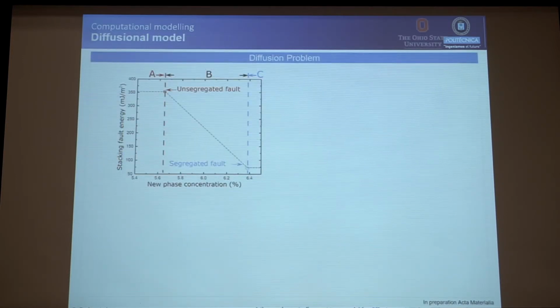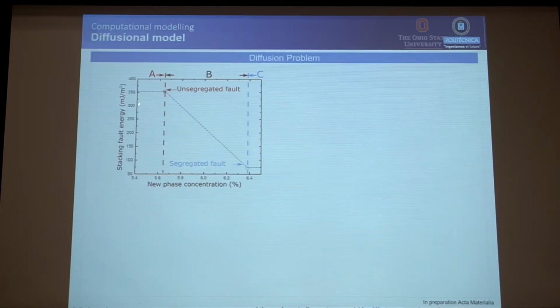So the diffusion field, basically, as I said here, the chemistry, so this is the stacking fault energy, again. So the stacking fault energy depends on the chemistry. This will be an unsegregated fault, so without changes in chemistry. You can see here a high energy coming from the ground neighbor. This is data from the literature coming from DFT. And then if you have a fully segregated fault, it will be a much lower energy fault, so the dislocations will start shearing much faster.